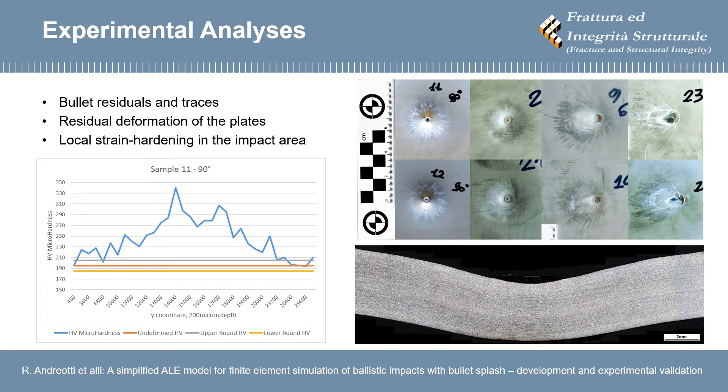The sample plates were experimentally analyzed to collect information in terms of bullet residuals and traces, residual deformation of the plates, local strain hardening, and the impact area by means of micro hardness measures along the section of the plates.